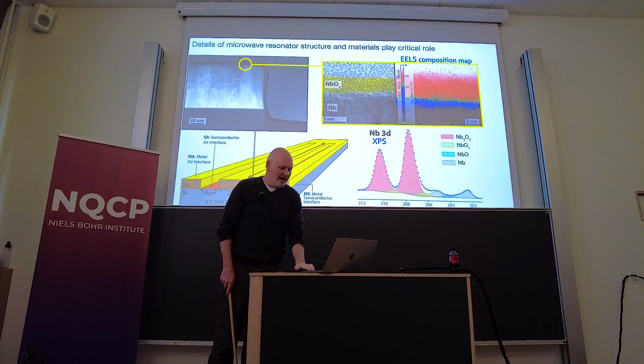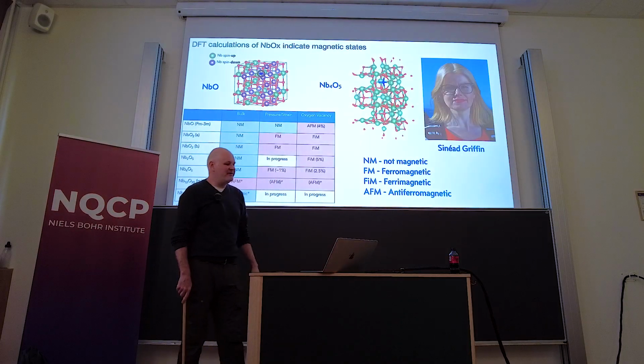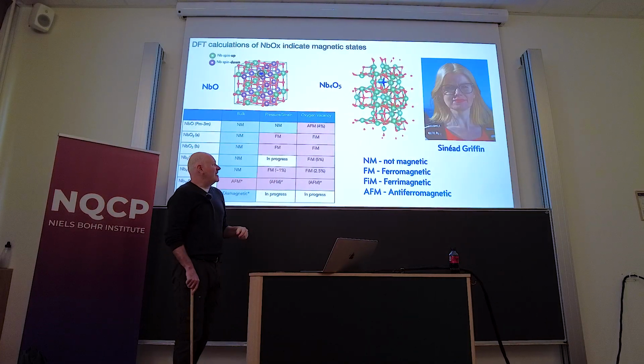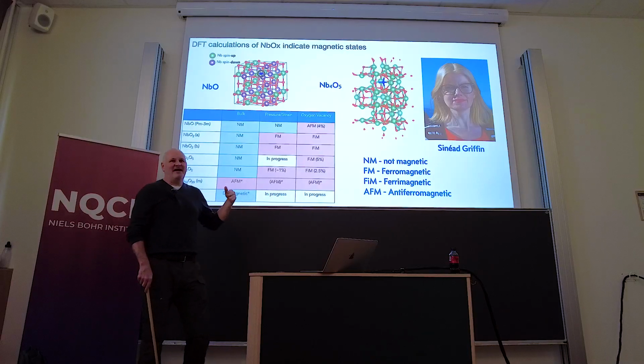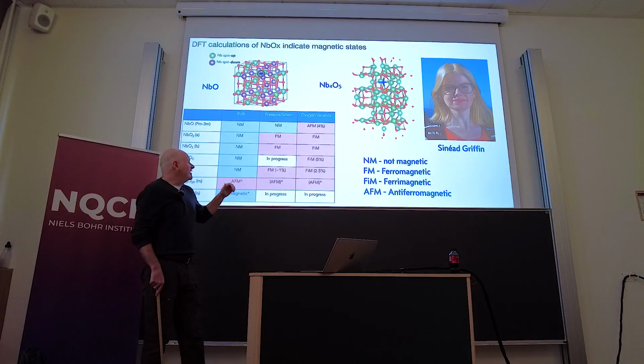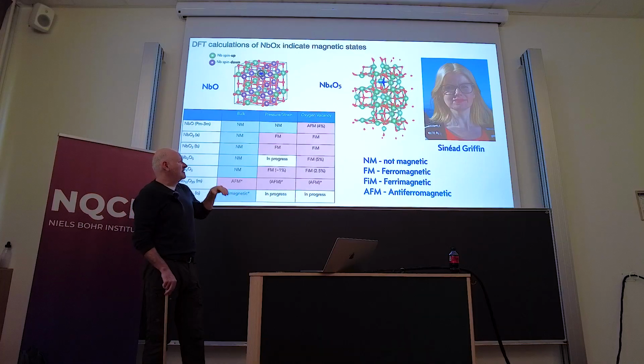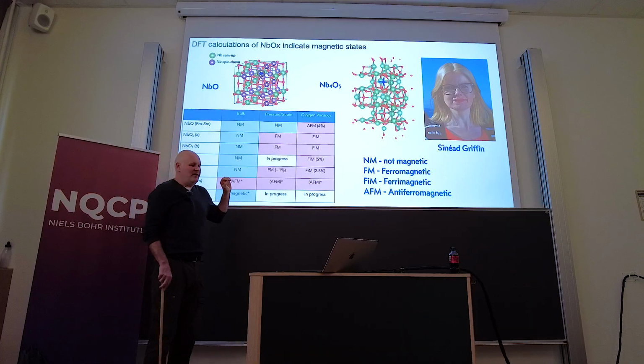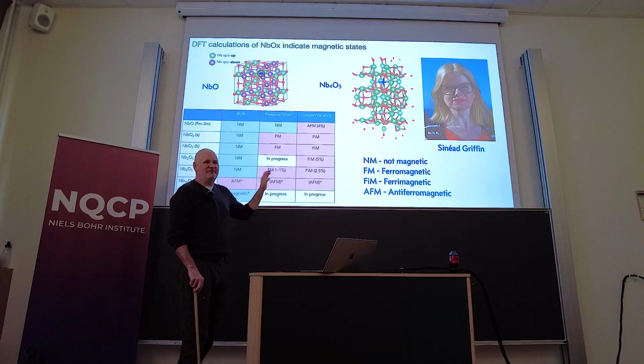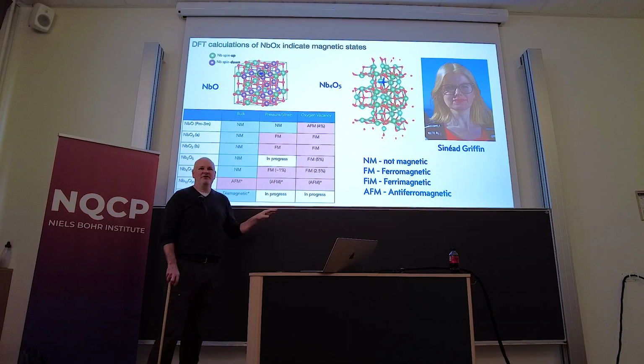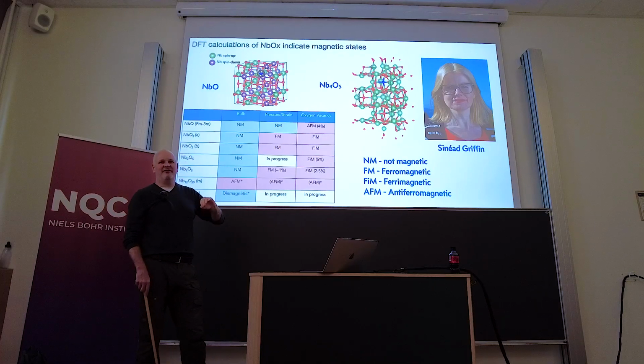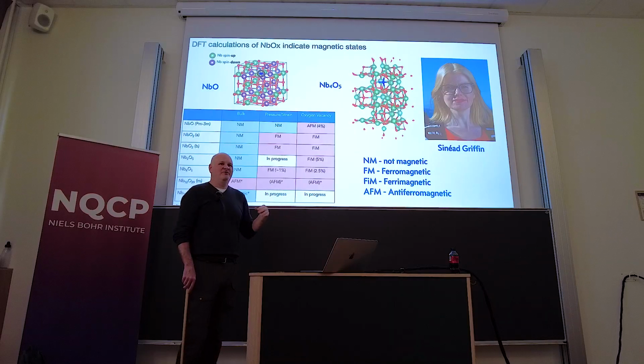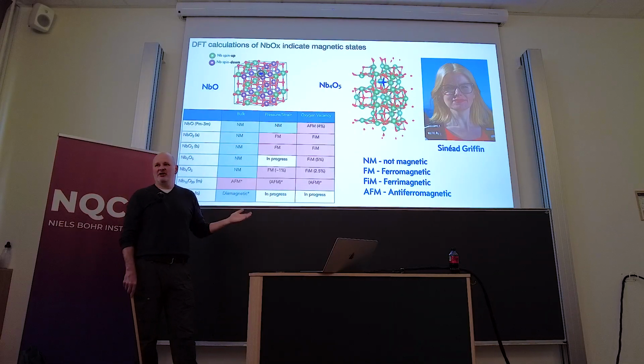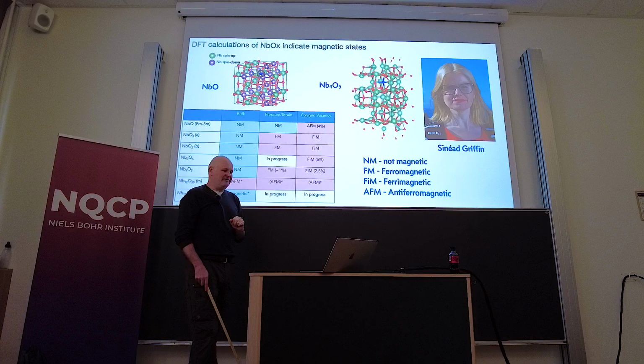And then we have another collaborator at the Molecular Foundry, Sinead Griffin, who's a theoretician. And she went through and took all of the oxides that we found in this lab and did calculations on essentially the structures and what the magnetic impact of these materials are. And it turns out that the Nb2O5 is a non-magnetic material. However, anything off stoichiometry from pure Nb2O5 has some magnetic properties, which is really not what you want for superconducting qubits. You want to avoid any magnetic materials.